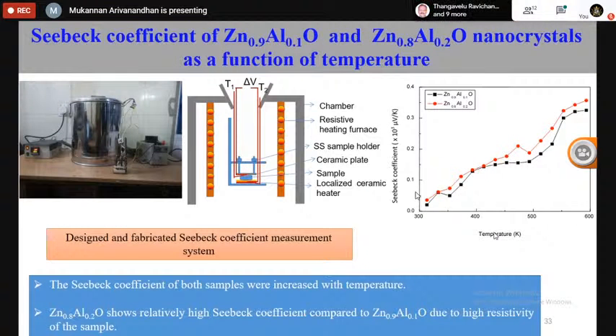Okay, and then the Seebeck coefficient has been measured by using this indigenously fabricated thermoelectric system. So this is a vertical thermoelectric system where you can place the sample in between the hot end and cold end, and you can have thermocouples at the hot end and cold end, and by using that you can measure the temperature difference as well as the thermo EMF, and the same thing can be inserted into the external furnace. There you can measure the Seebeck coefficient at different temperatures.